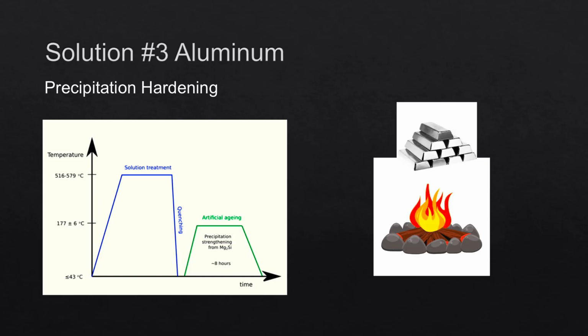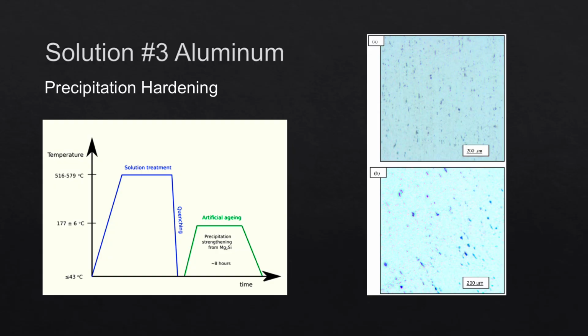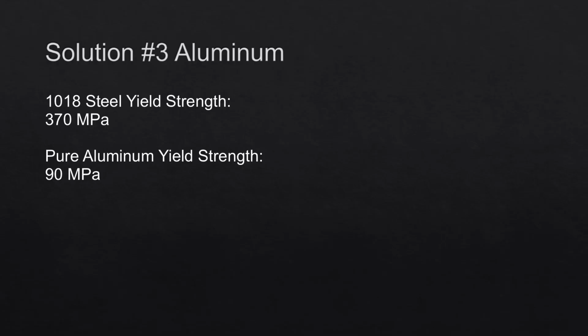The alloy is heated up to and held at 525 degrees Celsius for roughly an hour, allowing the alloying elements to dissolve evenly throughout the aluminum solution. The alloy is then quenched not for the purpose of hardening, but to ensure that precipitates aren't formed during cooling. This stage is called a T4 temper and remains relatively low in strength.